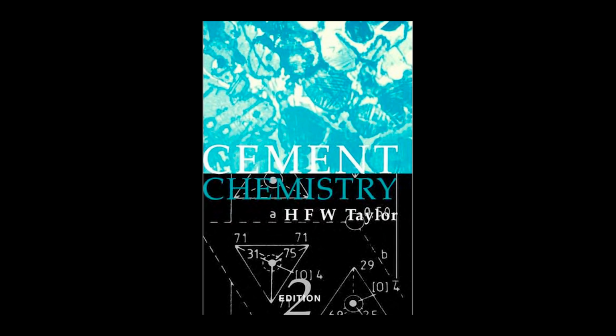Okay, so once we take that finished clinker, grind it with gypsum, and add water, we start what is arguably the most important chemical process in the world: hydration. What are the two main products formed when the silicates, C3S and C2S, meet water? They form two primary hydration products: the poorly crystalline calcium silicate hydrate gel, or CSH, and crystalline calcium hydroxide, or CH. The CSH gel is really the engine of concrete.